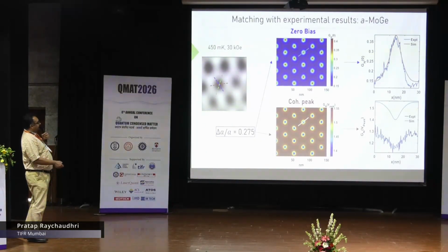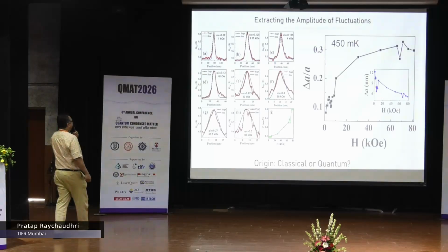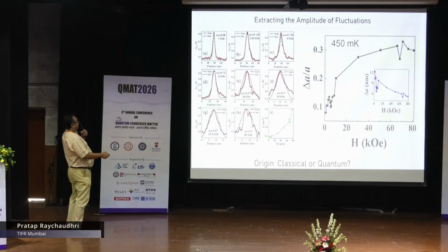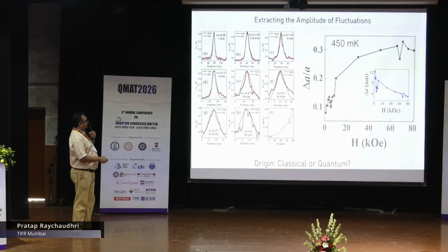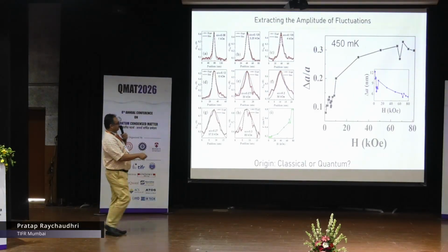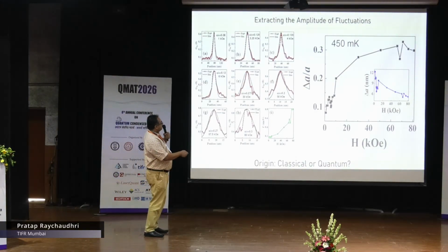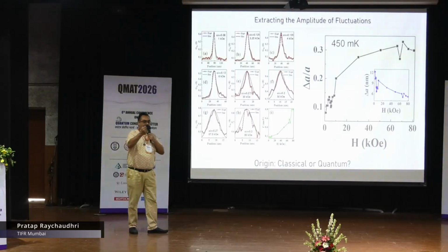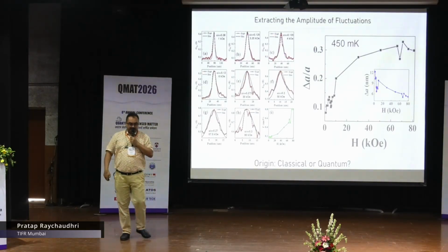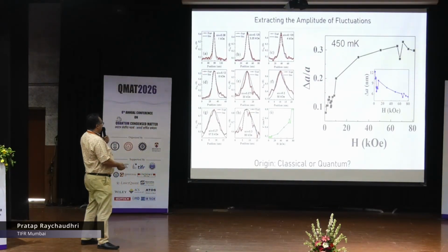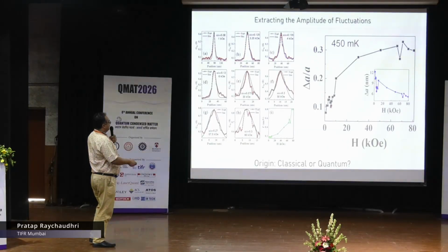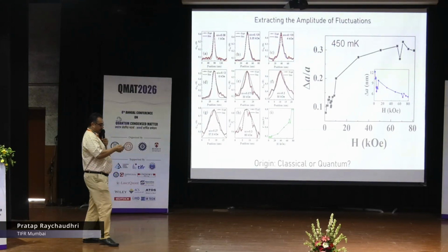Nevertheless, I can use this zero bias conductance and do this fitting at various fields. And now what I see at 450 millikelvin is that delta A by A increases with magnetic field roughly like this. So remember, this is the relative fluctuation amplitude with respect to the lattice constant. The question is, can this variation come from thermal or quantum fluctuation?